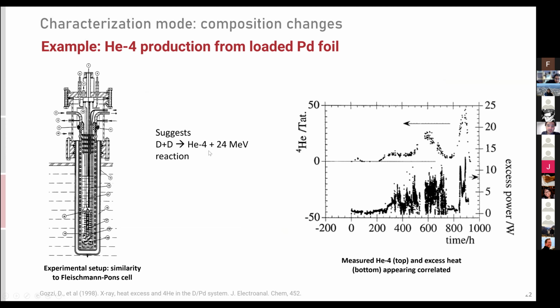And so for reasons I won't go into right now, people expected helium to be a major source here, and so they tested for helium. And in this setup, which is very similar to the Fleischmann-Pons cell done at the University of Rome, they found that it also measured excess heat, the same kind of heat measurements as in the Fleischmann-Pons experiment, which are seen down here.